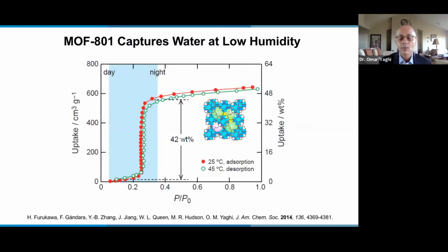Now, there are desiccants known to take up water at room temperature, but then you have to heat them up to over 200 degrees C to get the water out. But in this case, because of the metal organic composition, we can modulate the hydrophilicity of the pores and be able to remove the water at fairly mild temperatures. So for people like me who grew up in the desert, this is ideal for harvesting water from desert air, because during the night I can take up the water, and during the day when it heats up, I can remove the water. And the fact that I have this very sharp knee isotherm means that my working capacity is maximized.